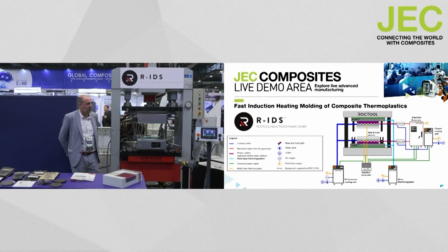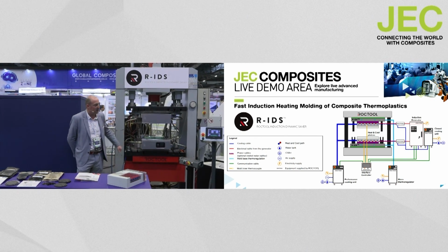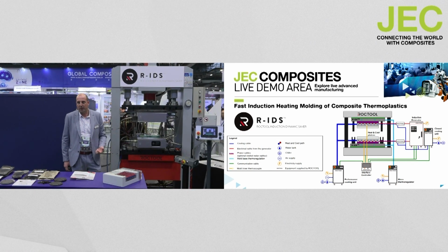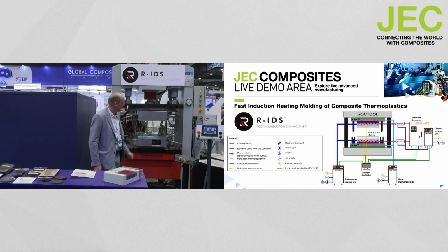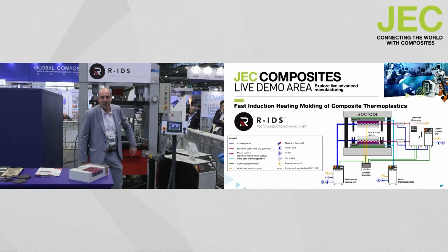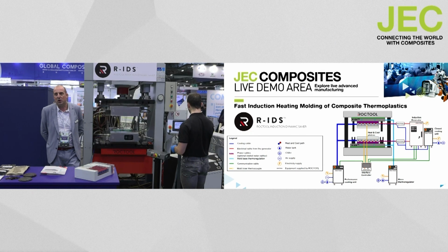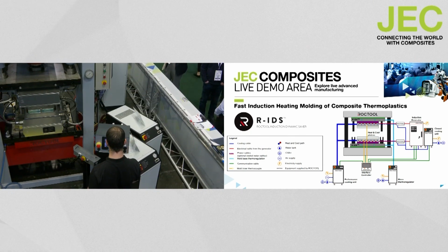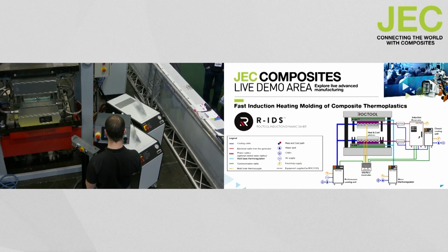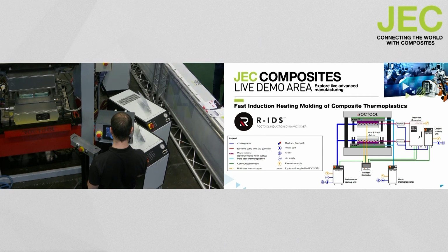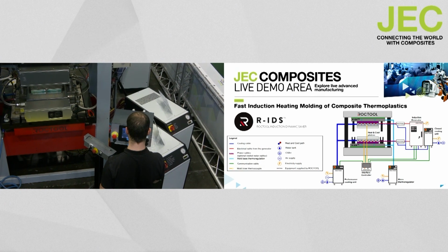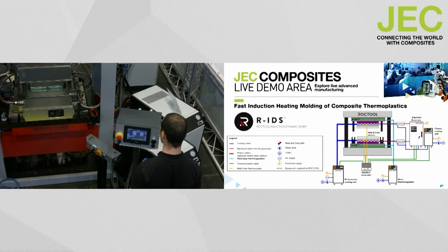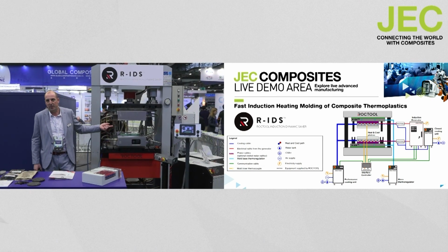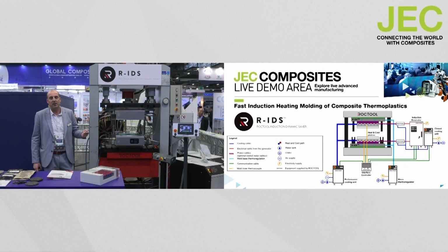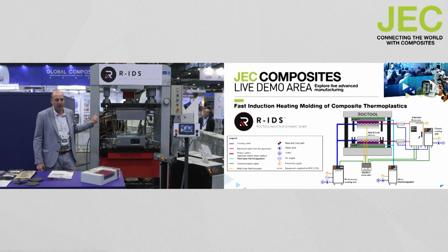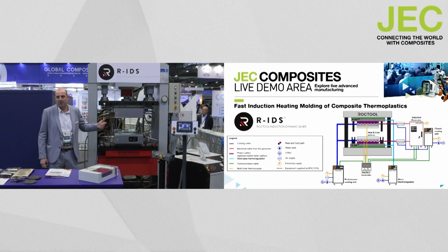So in this Roctool Induction Dynamic Saver technology, we have an induction system. And to use this technology, we need to have our equipment. So on the right of the demonstration, you have our Roctool generator. It's a dual zone equipment, to be able to manage separately the top and the bottom of the RIDS system. So we have one connection for the top, a second connection for the bottom. And with these induction generators, we also have two cooling units because we also have integration of cooling channels inside the hot plate. One is dedicated to the mold. It's equipment with the capability to deliver 100 liters per minute at 20 degrees from a chiller group. And the second one is because our generators need to be cooled.